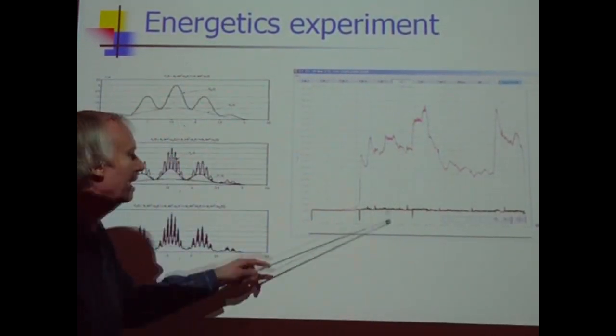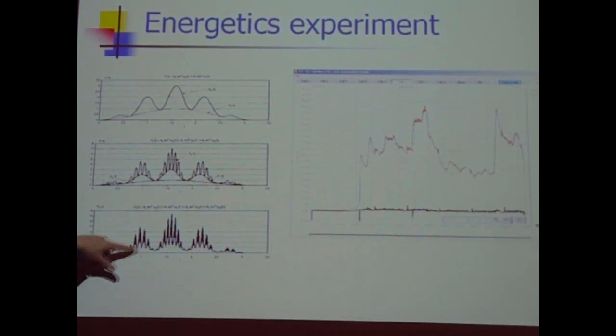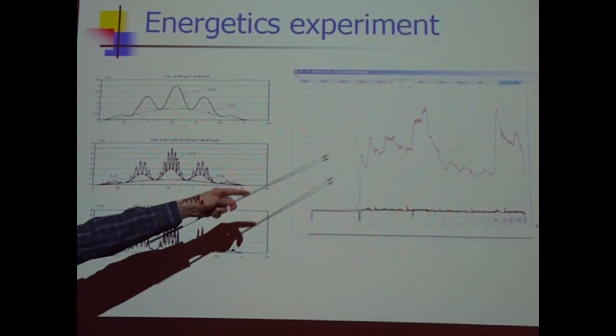We talked about the very high excess power result in the energetics experiment, and we talked about the super wave, and remembered the stuck desk drawer that we're yanking, trying to pull free. Now, if you think about it, this is run in galvanostatic mode, so the current's being controlled. The current's being forced to follow this complicated pattern. This is the electrochemical current. Electrochemical current's high, you bring a lot of deuterium to the surface, the electrochemical current goes back down, some deuterium comes out, make it high, it goes in, it goes out. So this current protocol is one which is going to maximize the flux of deuterium across the surface. In a sense, retrospectively, if flux is really important, it's probably not surprising that a gigantic result was obtained with this very interesting current protocol.